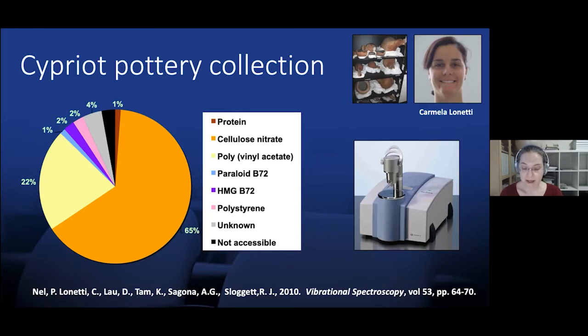I used acetone-dampened cotton wool swabs to remove microsamples of adhesive from a vessel, which was then wiped over the flat diamond window. With the evaporation of the solvent, this left a microfilm of adhesive from which an infrared spectrum was obtained. Each spectrum was immediately matched against the in-house database that was built using reference adhesive samples before we commenced the collection survey. If a spectrum was poor, this was immediately rectified.